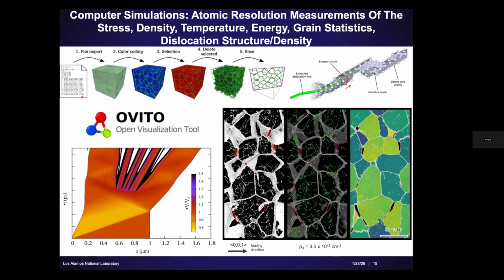So those of you who are not familiar with molecular dynamics, it's essentially you're solving Newton's second law of motion, essentially F equal to ma at the atomic scale. You can extract that position time plot like I showed you during the shock simulations. You can simulate the grain structure in a material. Now I'll put a caveat there. When I say grain structure, sure, you can have the morphology of the grains, but we're limited in terms of how large our grains can be. So usually, the grain size is a few nanometers, whereas experimentally, the grains are tens of microns. So the point here is that we're trying to get qualitative insights from molecular dynamics, not necessarily solve the whole problem and get quantitative information.